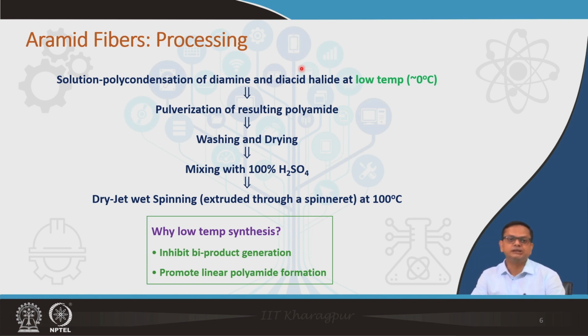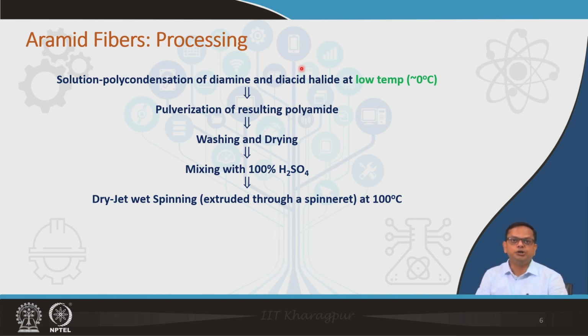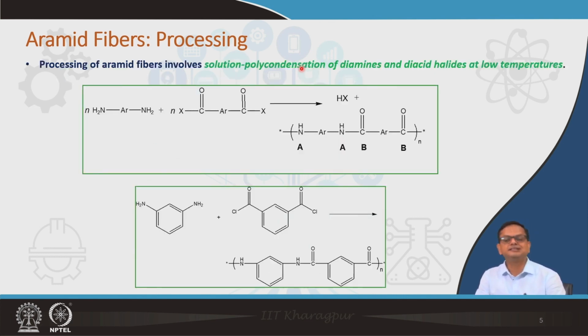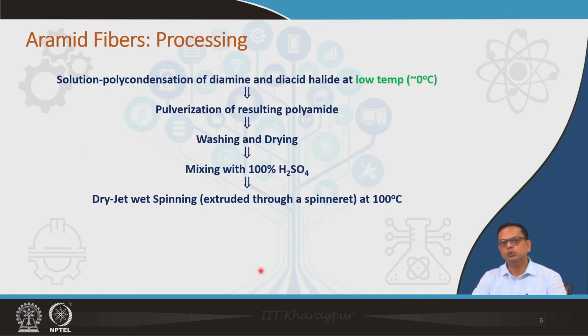and another again very important factor is to promote linear polyamide formation. We do not want any kind of cross linking to take place, ideally speaking, we should not be having any cross linking or any other kind of structure formation. It should be a linear structure, because if you go for a linear structure, then axially the strength is higher, modulus is higher. So, that is why the whole reaction is done at lower temperature.